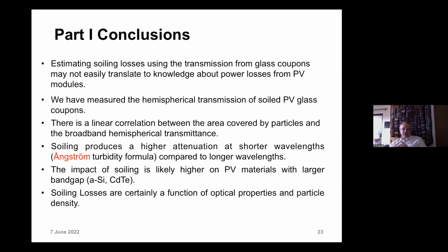And the impact of soiling is likely, therefore, because of this spectral approach, higher with PV materials with a higher band gap. The blue-rich area of the solar spectrum is affected more by soiling than the red-rich area. So it's going to depend upon that. And so the soiling losses are certainly going to be a function of the optical properties, for instance, the optical properties of the particles and the amount of particles per unit area.